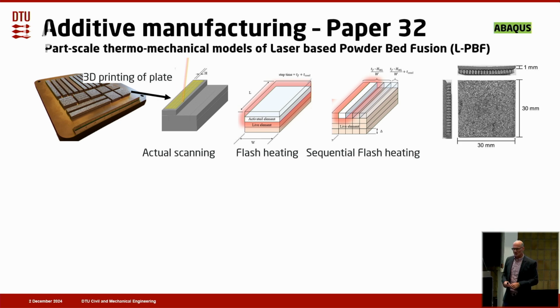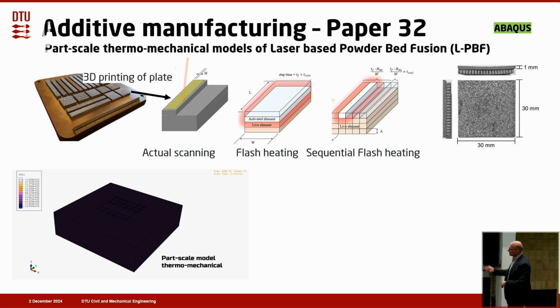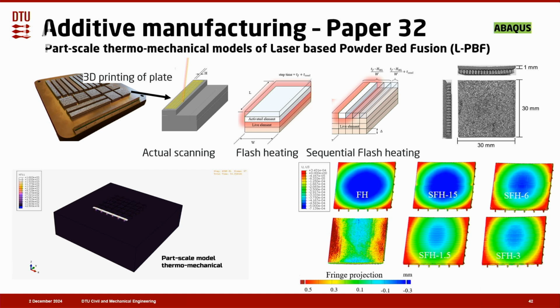And we also suggested the so-called sequential flash heating. This is where you get some information about the scanning strategy taken into account. This also suffered from bending when it was cut off from the building plate. So this is the simulation of this. And we could see here that when we used the flash heating, we got something that was almost rotational symmetrical. But when we used the stripes in the sequential flash heating, we got something that was closer to the experimental results, that was this.